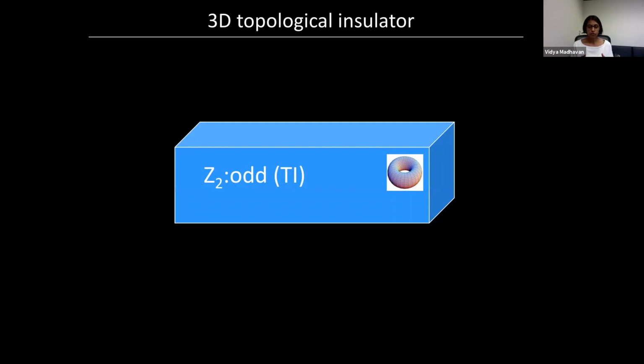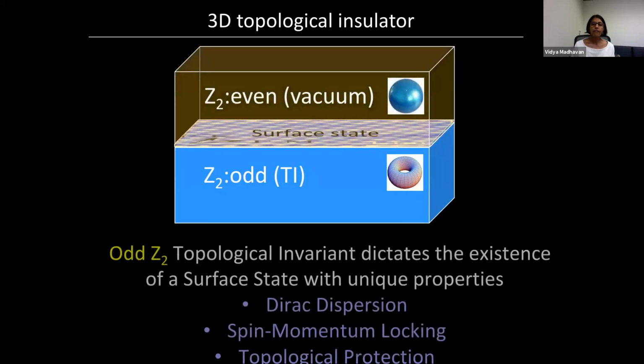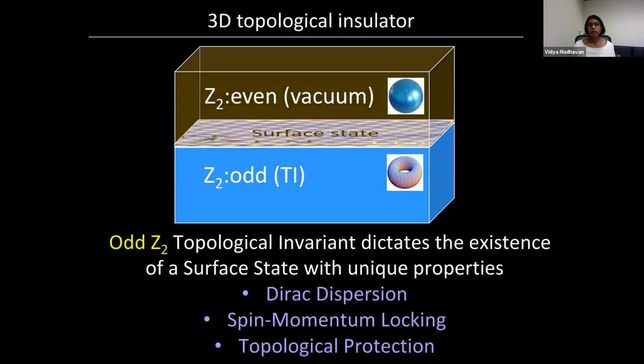So let's say you have such a 3D material, which is a topological insulator. The interesting thing about such a material is that because of the topology of the interior, the boundaries of this material must have very special states which only live on the boundaries. These are two-dimensional states which live on the boundaries, and these two-dimensional states have very unique properties. One of the properties is that they have Dirac dispersion, which is that these electrons behave like massless relativistic fermions. The other interesting thing is that as long as the topology of the bulk is not changed, these states are never destroyed.